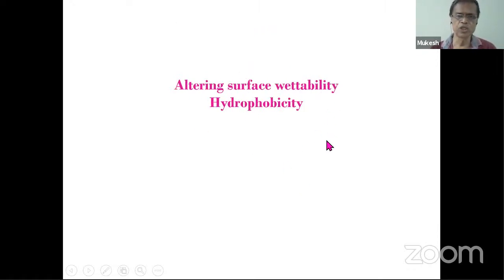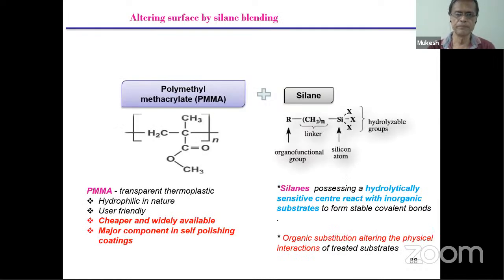Hydrophobicity is another approach. That means surface wettability. If the material is hydrophobic, that means it prevents water. If it is hydrophilic, that means it's more of a water loving. So can I create hydrophobic surfaces and see how these hydrophobic surfaces have an impact on the bacterial attachment? So we used silane. As you know, silane, different types of silane. This is polymethyl methacrylate and silane. So we can modify this and produce different types of silanes which will have different hydrophobic nature and coat it on polymethyl methacrylate surface and see the bacterial attachment.